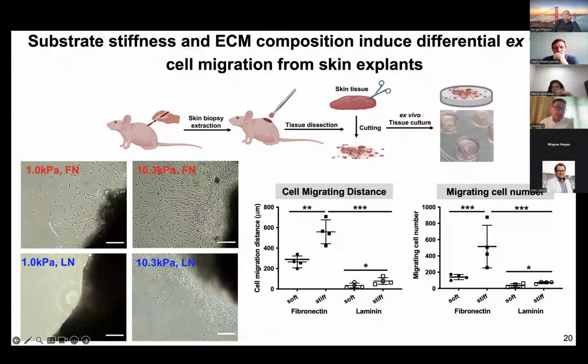You can see how these cells are actually migrating through the matrix, from the tissues into the substrates. As you increase the stiffness, you actually get more cells migrating, and not only is the distance further, but also the population of the cells. Now, if you change the substrates to laminin, you see that the cells barely adhere to the surfaces, with a significantly lower number of cells adhering.